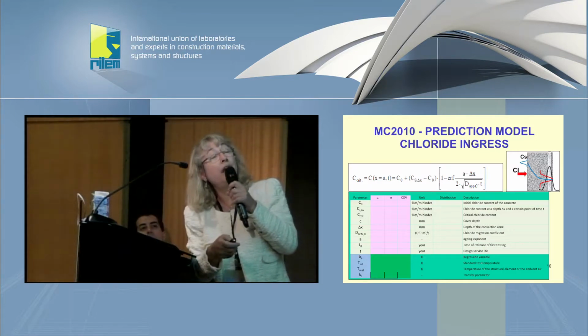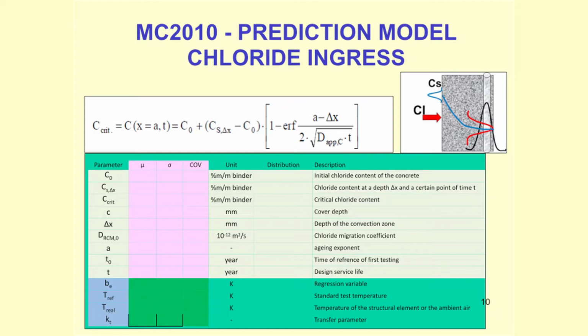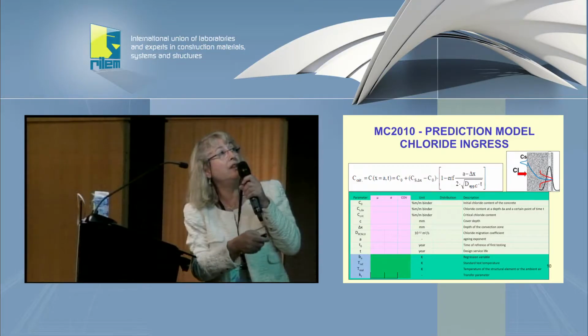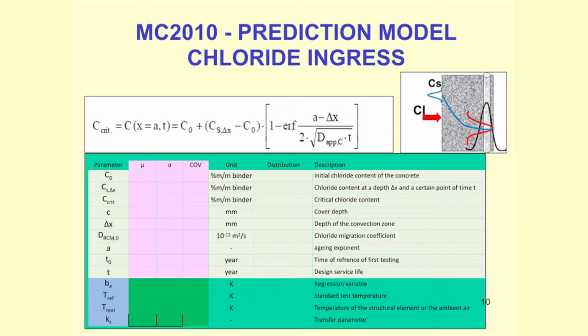About this model, we need to consider, as with probabilistic treatment, that we will have a distribution of the surface concentration, a distribution of the diffusion coefficient and the aging factor, perhaps the convection zone also with a distribution, and a distribution of the position of the bar. For solving the equation in a probabilistic manner, which you can do by Monte Carlo or other tools, it's necessary to have a mean value for each of these parameters: the initial chloride content in the concrete, the surface concentration, the chloride threshold, the cover depth, the convection zone, diffusion coefficient, aging factor, and the time at which you are accounting for the aging factor, at which time you make the first test and the further test. And it's necessary to have the mean, the standard deviation, and the coefficient of variation.